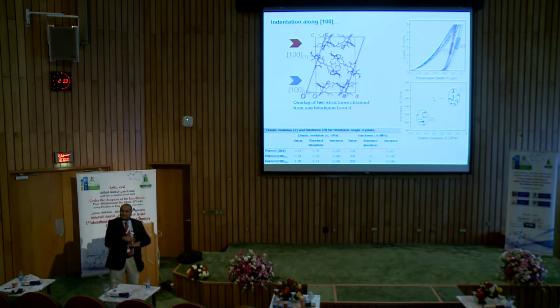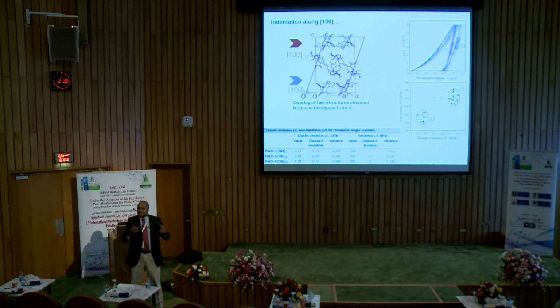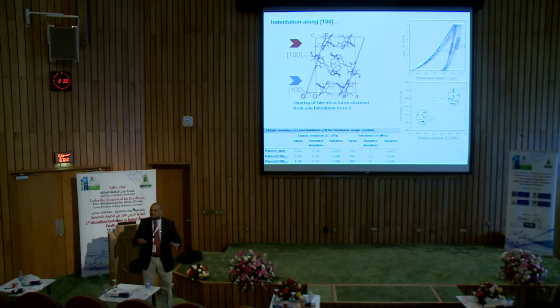We just do these experiments hundreds of times, and you can see from this load in depth curve, here it's very clear, right? So I get two distinct responses. They essentially partition themselves into very clear two bins of response. And just to illustrate that, I plot hardness versus modulus. So there's one group here, one group here. And there are some points in between which probably are at the interface of these domains.